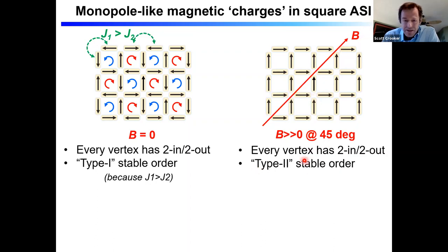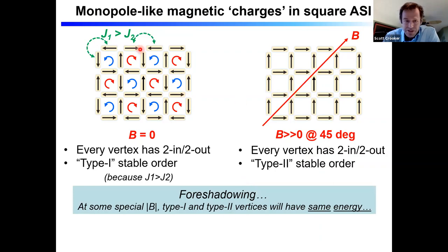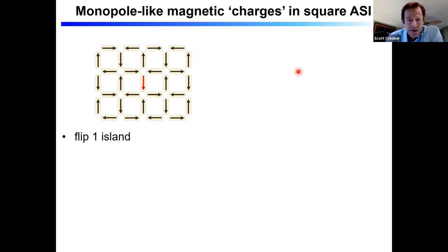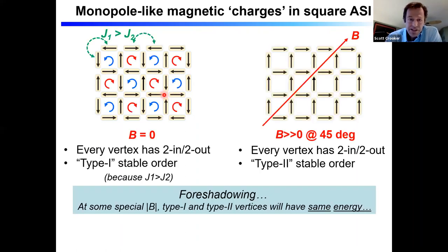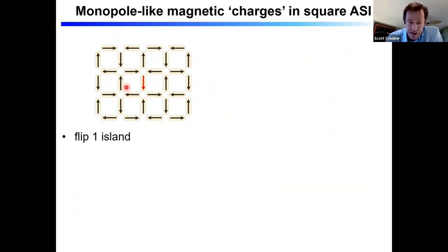And just to employ a bit of foreshadowing, you can imagine at some special magnetic field between zero and large, the energies of these two types of vertices are going to be equal or degenerate, and interesting things are going to happen. So let's talk about how we get from this situation to this situation. This is where monopole excitations come in. So if we start with a stable type one ordering and we flip one spin, okay? But let me just go back to the previous slide. Clearly, to get from this situation to this situation, I'm going to have to flip individual islands. So let's see what happens when we start flipping islands.